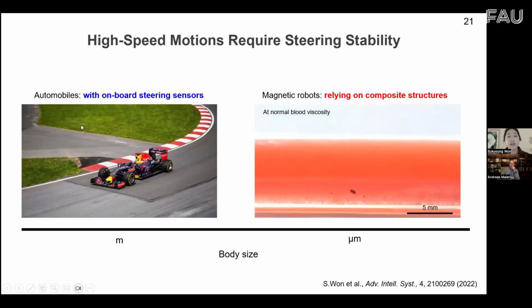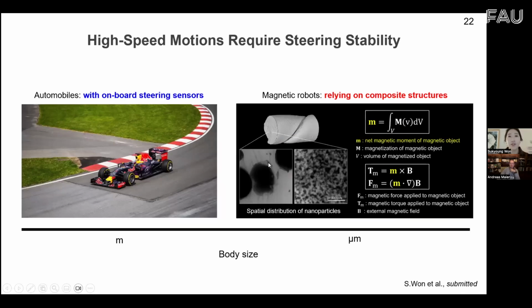For example, automobiles usually use the onboard steering sensor to control their direction at a high speed. However, for miniaturized robots, the steering stability depends on their composite structure. Even in a blood-like environment, these microrobots show the adaptability to climb obstacles. However, this non-uniform nanoparticle distribution may have a negative impact on robot performance through non-uniform magnetization and uneven magnetic torque and force generation.